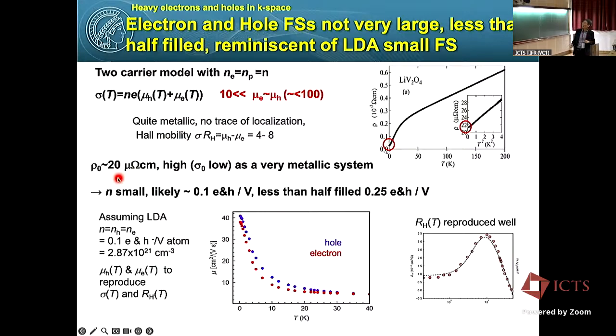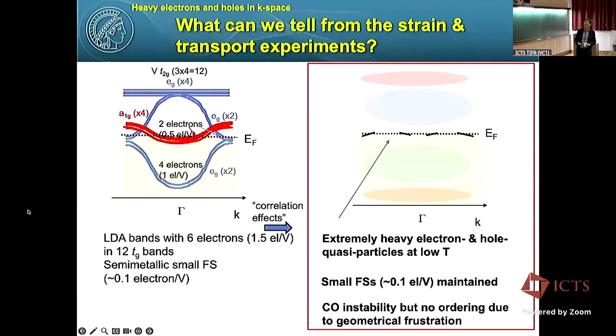But to have such high resistivity with metallic conduction, to have such high mobility, our carrier density must be small. And this gives us a carrier density of roughly 0.1 electron per vanadium, consistent with LDA calculation. In fact, if I assume equal number of electron and hole, 0.1, we can reproduce the Hall effect and resistivity very well. And we see a reasonable temperature dependence of mobility up to 40, 50. So it looks like we have a small Fermi surface.